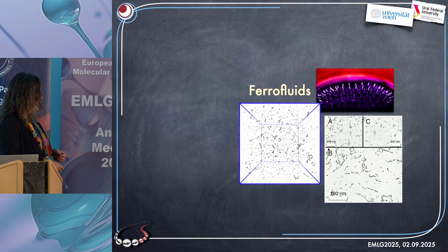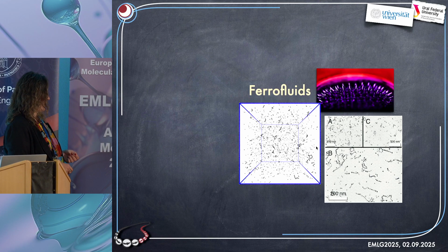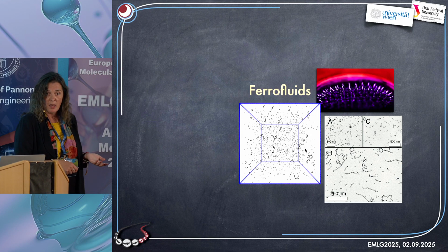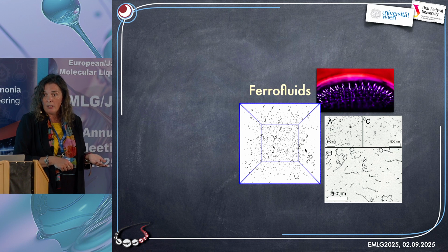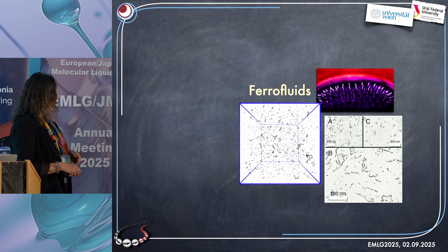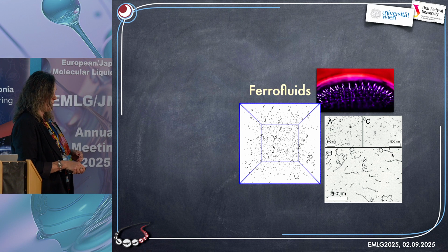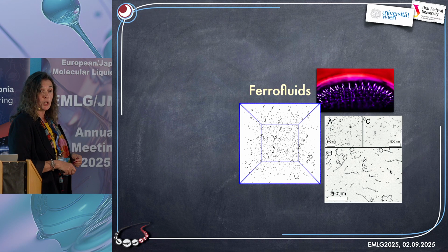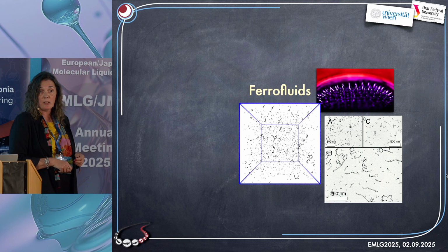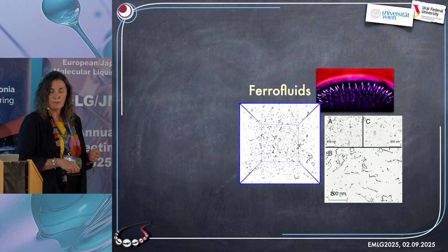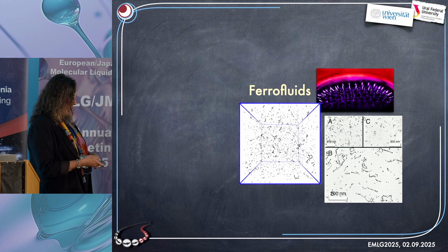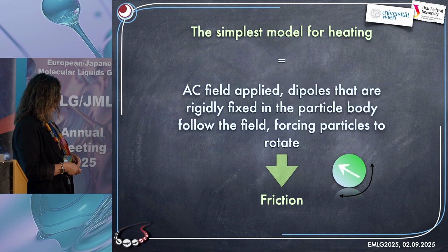So do we want to have chains and rings in blood vessels? Well, it depends on their size. In principle, it's not such a bad thing, particularly considering that a chain is very responsive to an applied field. But what about rings? Rings are closed form. They have a zero magnetic moment. So rings are bad. Okay, now, can we quantify that?